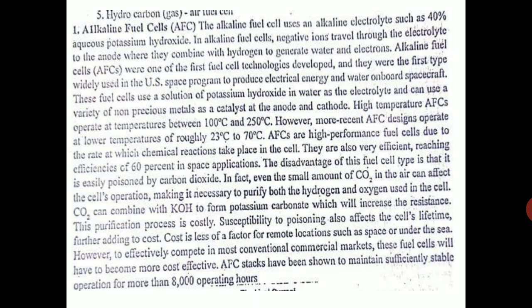Alkaline fuel cells have been shown to maintain sufficiently stable operations for about 8,000 operating hours, so they definitely have a long life. Research is ongoing to make them more economical. One bottleneck is CO₂, which is present in air at about 400 ppm. This reacts with the KOH electrolyte to form potassium carbonate, which increases resistance and reduces current, making AFCs less popular in commercial use.